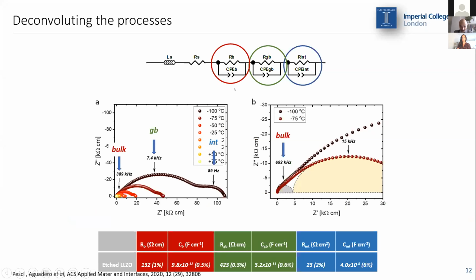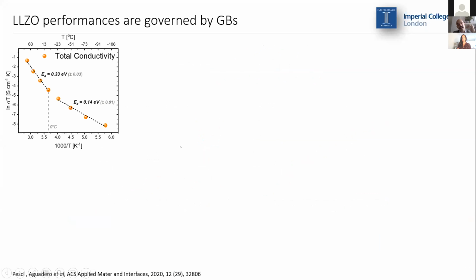And if we fit our data, we can end up with values of resistance and capacitance for the three processes. And if we actually take the data recorded at different temperatures, we can plot our conductivities as a function of temperature. So interestingly enough, we saw that the total conductivity of gallium doped LLZO actually had two different values depending on the temperature. So a higher value of activation energy at higher temperature, and a very low value of activation energy at temperature below 0 degrees.